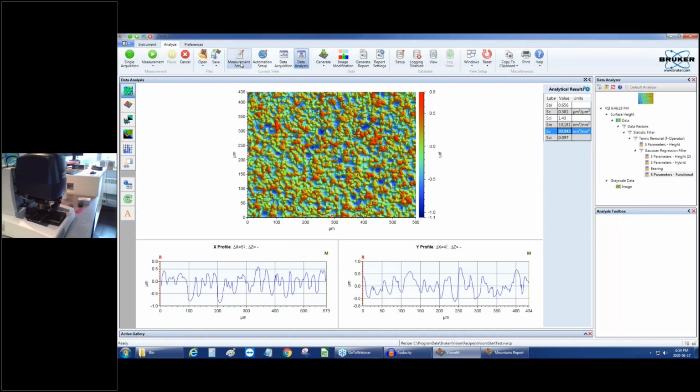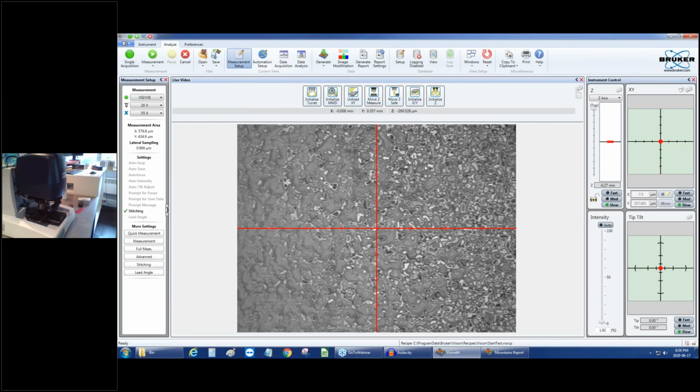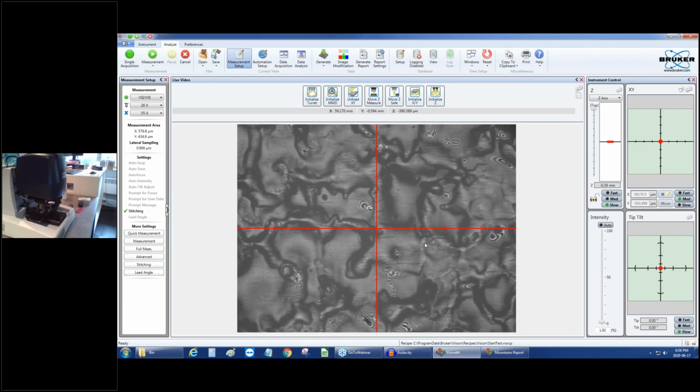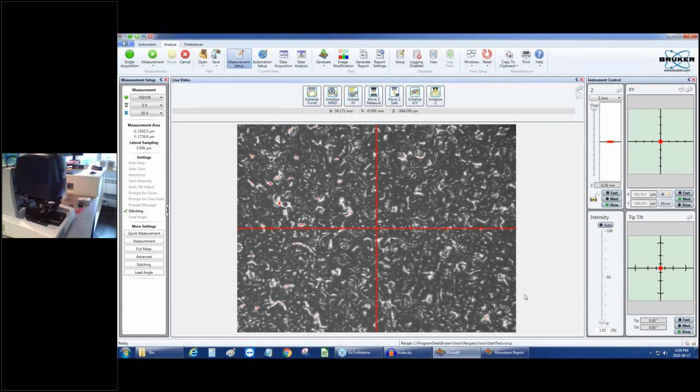But now, since we have all that set, we can compare surfaces. So this is the lowest grade of EDM, which is really the finest one. If I move now toward different scales, where we will get rougher surfaces obtained. Yep, so now let's find a focus. So now you see the 20x does not encompass many of this motif. So it will be better in that case to capture the reality of that surface to zoom out with the 5x, and get a larger field of view and get enough of this pattern to be described. And in that case, I can quickly get the result with one single measurement.